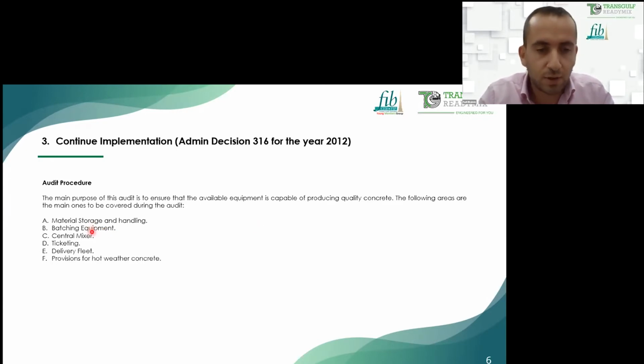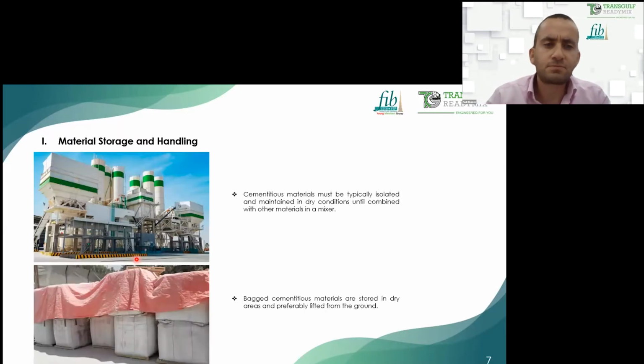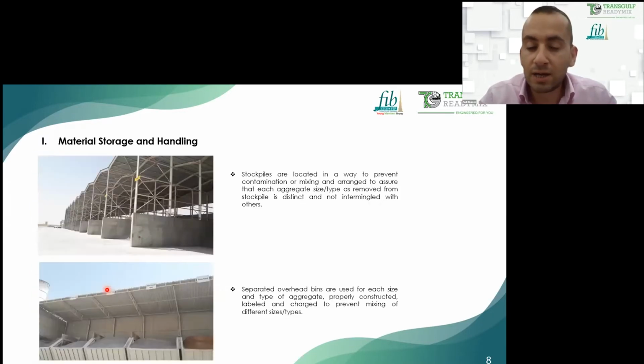They will go through the audit checklist, the requirements of this audit: material storage and handling, batching equipment, central mixer, and provisions for hot weather concrete. This mainly affects the sustainability. They go through the material storage and handling. They make sure that all the cementitious materials are stored in suitable conditions. For example, bagged cementitious material must be stored in dry areas, lifted from the ground. Aggregate must be stored in separate stockpiles, with no mixing, even for the overhead bins.